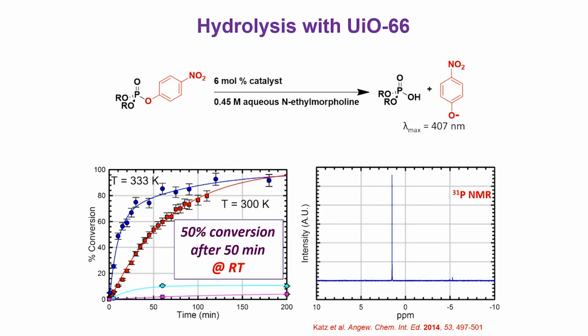So when we did that, one thing to point out too, the half-life here is 50 minutes. And you might say, okay, is that good or bad? How can I benchmark what a 50-minute half-life means? Before this, I had a postdoc using supramolecular assemblies who spent 6 months to make 100 milligrams, and the half-life, which was the best back then, was 36 hours. And that was the best out there that is catalytic, with a half-life of 36 hours. Making 2 grams of this overnight, and after you process the material in 2 days, you have a gram of that. Going from 36 hours to 50 minutes was huge for us and for a lot of people in this area.